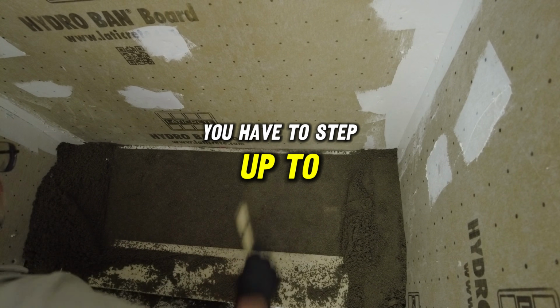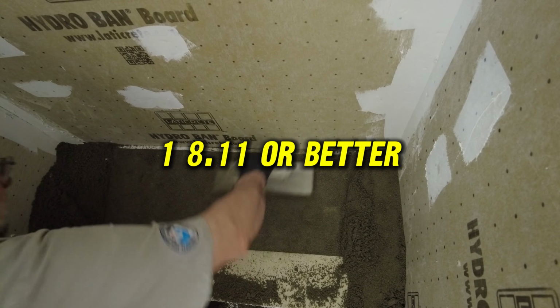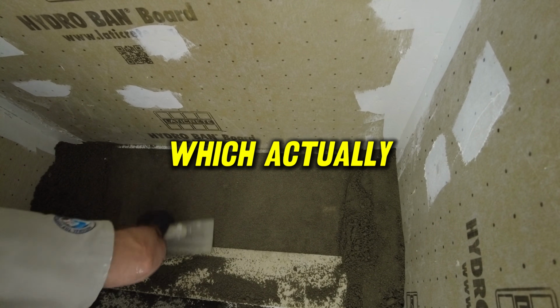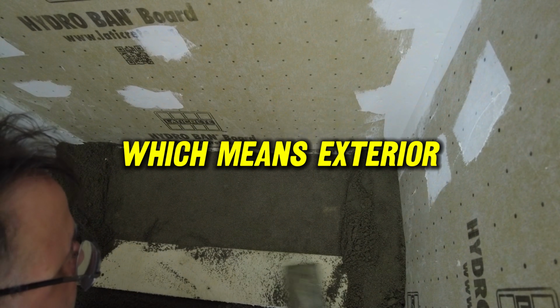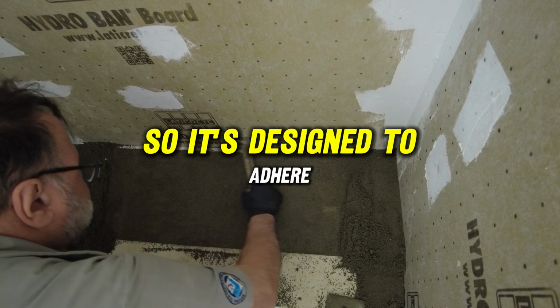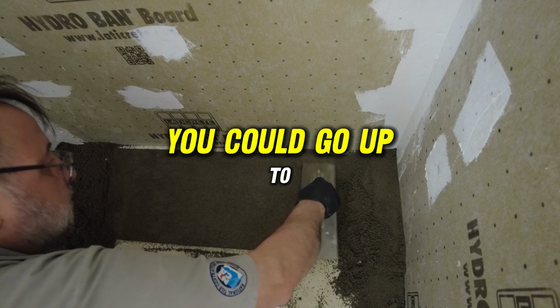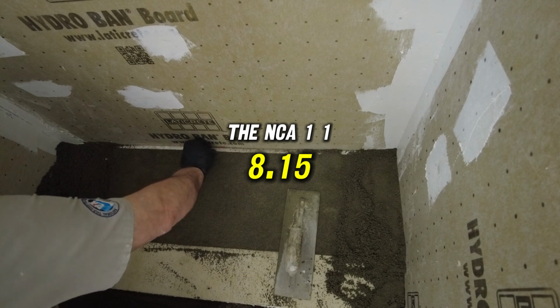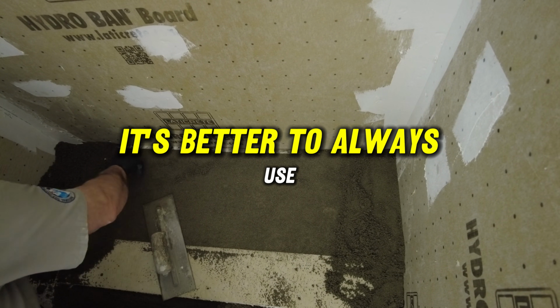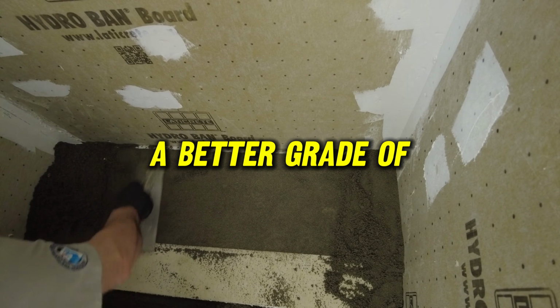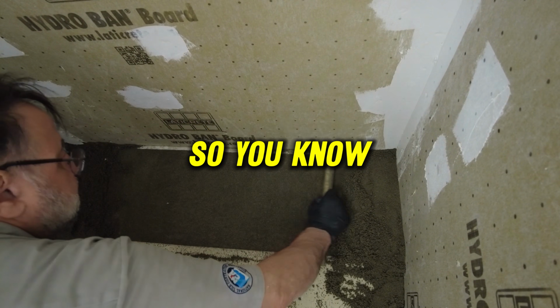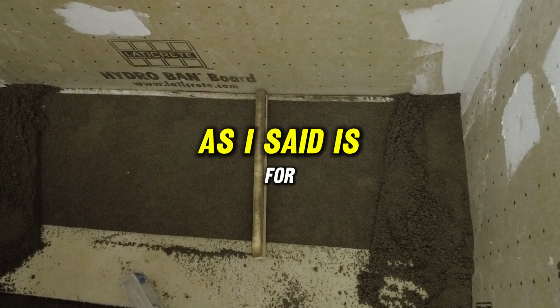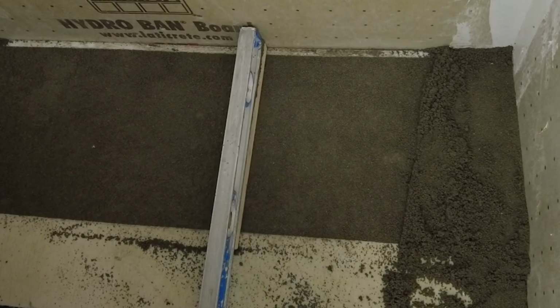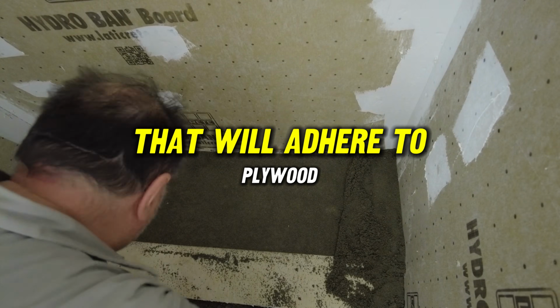You have to step up to the ANSI A118.11 or better, which actually, ANSI A118.11 is EGP, which means exterior glue plywood. So it's designed to adhere to exterior grade plywood. You could go up to the ANSI A118.15. In my opinion, it's better to always use a better grade of Thinset, so you know you got a very good bond. Now, the 0.11, as I said, is the minimum standard that you can use over plywood that will adhere to plywood.